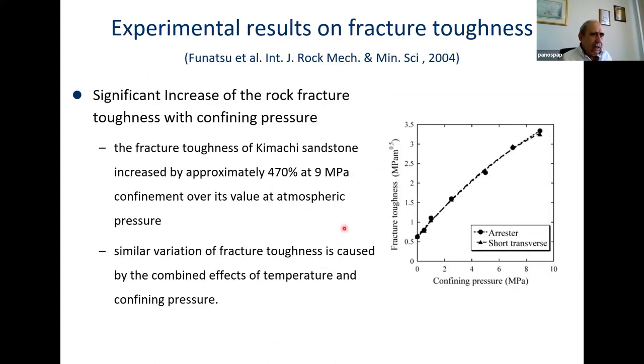And of course, to show you some results, I found these experimental results published in this paper, Funatsu et al. in 2004, in which they measure the fracture toughness as a function of the confining pressure. And you can see here the big increase in the fracture toughness as a function of the confining pressure. Under zero confining, of course, it's here, and under confining pressure of now 9 MPa, they had an increase in the fracture toughness by 5 times. And you can see that the diagram shows that it will still increase for higher confining pressures.